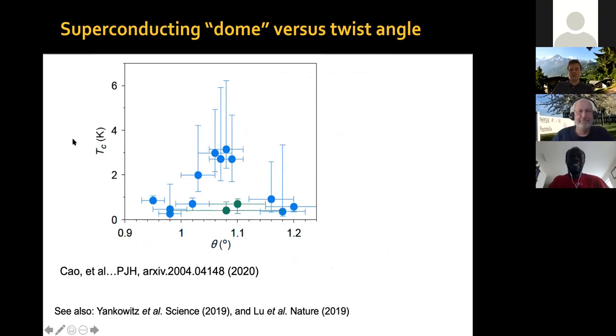Now, one of the things that I also briefly mentioned yesterday is that, by now, as we measure many, many more devices, we're starting to gather statistics about how these systems work. For example, now we can map the optimal doping TC versus twist angle for different samples, okay? And I put here over a dozen samples. These 2 green data points at the bottom have a lot of twist angle disorder, so the determination of the twist angle is not very clear, so don't pay too much attention to them. For the rest of the data points, you can see that there seems to be sort of a dome of TC versus twist angle, okay? The lowest twist angle for which we have measured superconductivity is about 0.95 degrees, the maximum about 1.2 degrees. And other groups have similar boundaries, maybe a group has seen slightly lower twist angle superconductivity also, maybe a little bit higher.